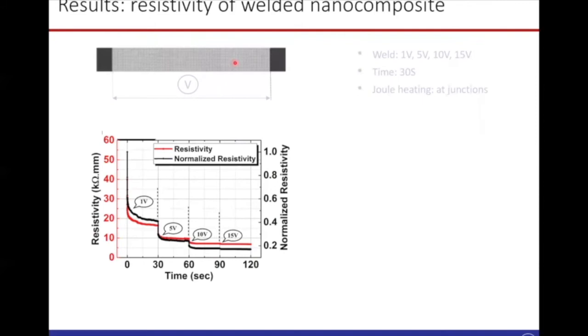Now we took this nanocomposite and applied a voltage to this electrode. We apply 4 voltages ranging from 1 to 15 volts for 30 seconds. As you apply the voltage, a small amount of current will flow through this nanocomposite and the current will heat the junctions of the nanowires, and due to the heating, the junctions will be modified. Here is the result of welding. We show the resistivity with respect to the time of welding at different voltages. As you can see, initially the sample resistivity is very high, around 60 kilo per millimeter.